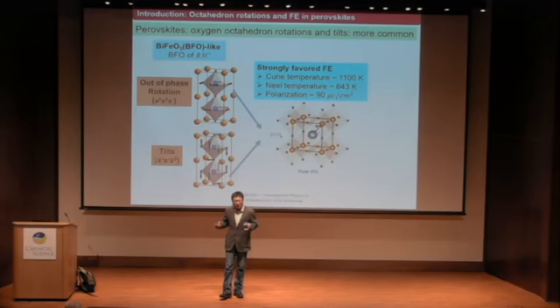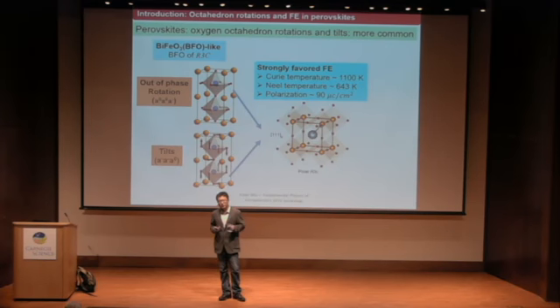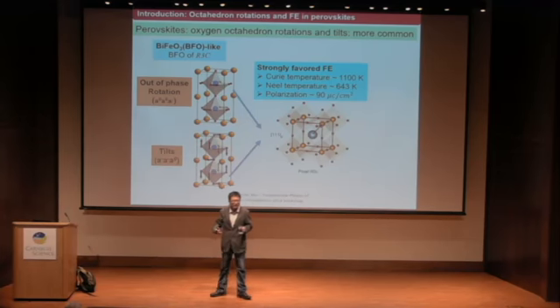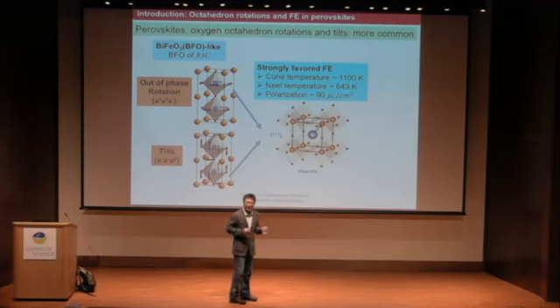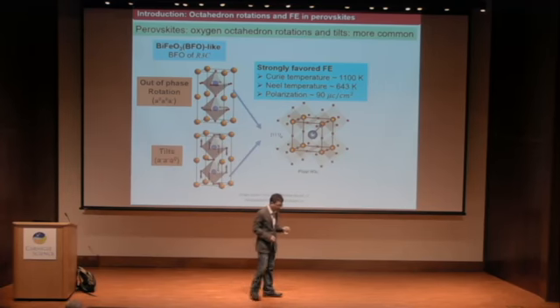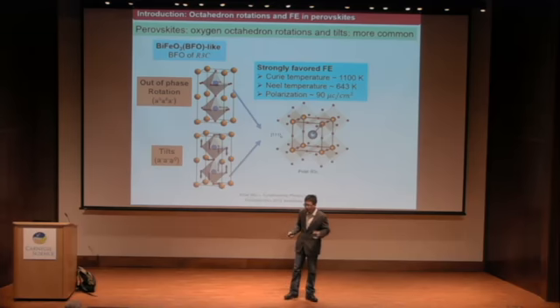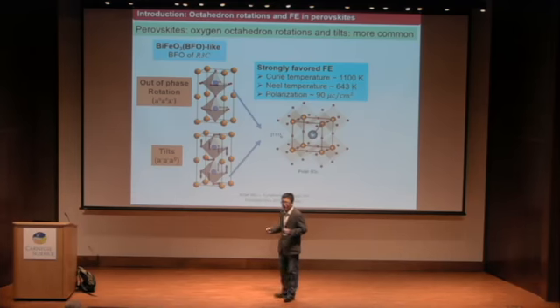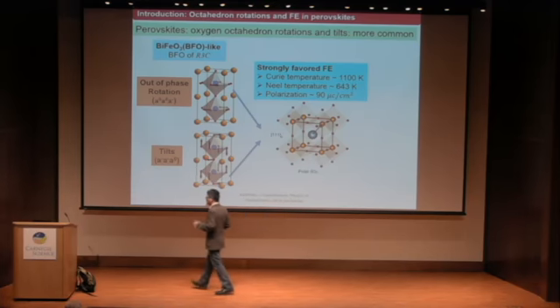We know that, of course, bismuth ferrite also promotes very large polarizations. Combined with other properties, for example the high Néel temperature and large polarizations and large Curie transition temperatures, bismuth ferrite, BFO, has been studied intensely in the last 10 years because it's a highly functional material.